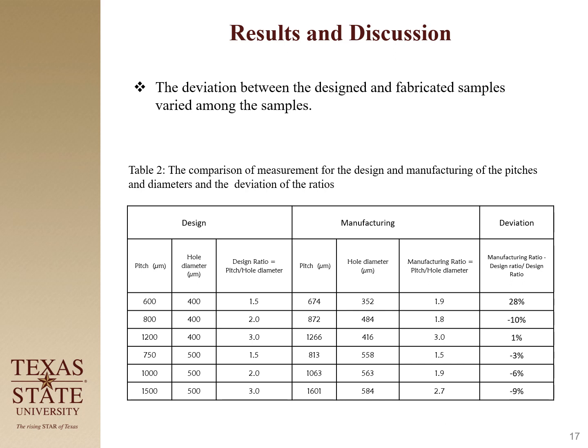Here I compare the design and the fabricated, and the difference between the ratios of the pitch to the diameter of the fabricated to the design is between 1 to 10%, except for the 400 diameter and a pitch of 600. Here it was about 27 to 28%.